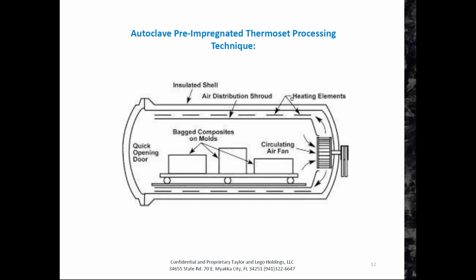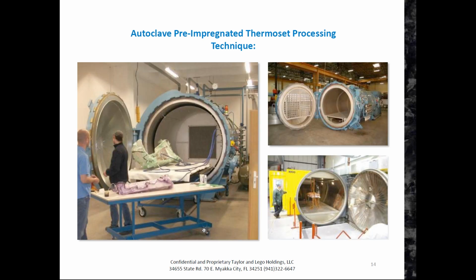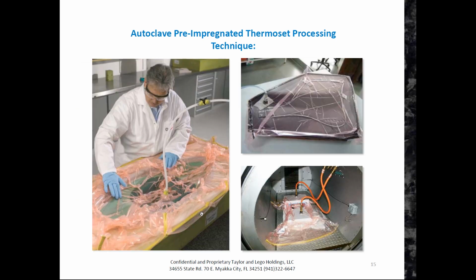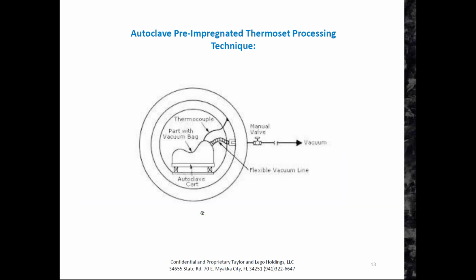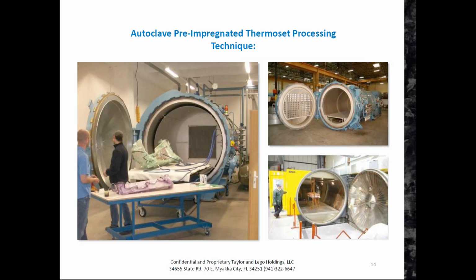The number 2 process is an autoclave approach, where sometimes they will use a more accurate tooling method. They might make a single-sided aluminum cavity mold, and then apply the materials to the inside of the cavity mold in a very similar fashion to what you saw in the wet layup, except that they're not brushing on the resin or spraying the resin. A lot of times they'll apply it through a vacuum type approach, or they will use pre-impregnated fabric materials, and that's really the most popular with this type of approach.